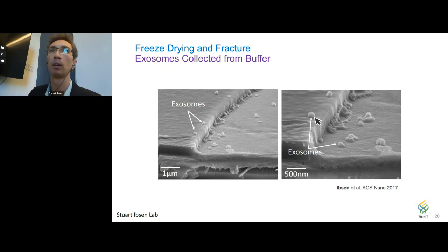And this is really exciting because usually exosomes are imaged using transmission electron microscopy techniques that dry them out and they kind of flatten out into a donut shape. But this freeze-drying technique preserves a lot of their original morphology. So we can see that they're not perfect spheres. They have their own texture. They have their own shapes to them. And I think there's a lot of interesting work to be done understanding this as well. But this is something that really shows these particles are being collected right there along the electrode edge, just like we see in the fluorescence images.